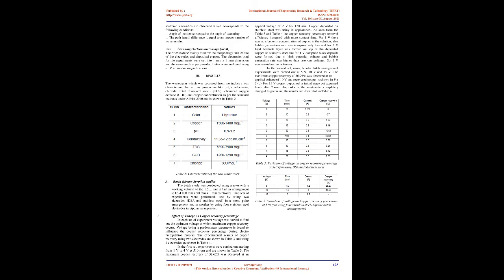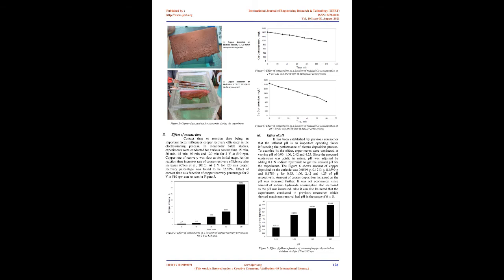Chemical oxygen demand of the wastewater was analyzed by the closed reflux titrimetric method. The reagents used for this analysis are standard potassium dichromate, K2Cr2O7, digestion solution, 0.1 M, standard ferrous ammonium sulfate solution, 0.1 M, sulfuric acid reagent and ferroin indicator. Wash the culture tubes and caps with 20% H2SO4 before use to prevent contamination. Transfer the 2.5 ml sample to culture tubes and add 1.5 ml K2Cr2O7 digestion solution to the vials. Carefully run down 3.5 ml of H2SO4 reagent into the vials, such that an acid layer is formed under the sample digestion solution.